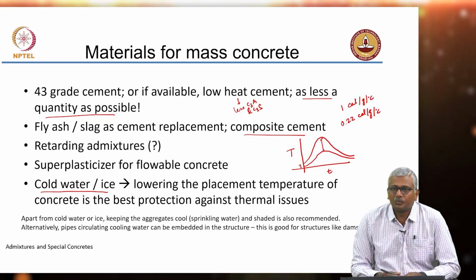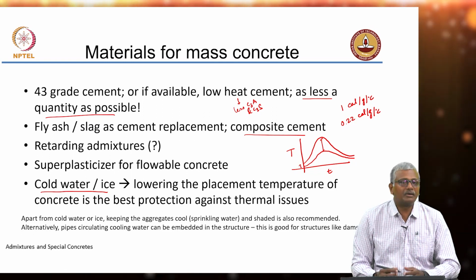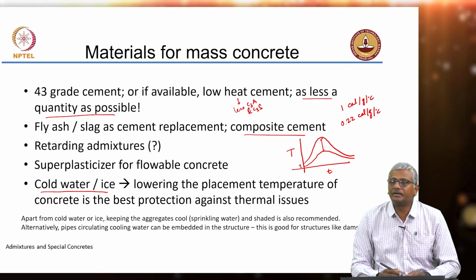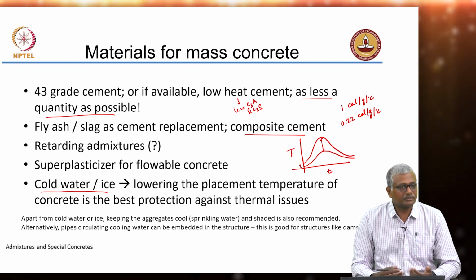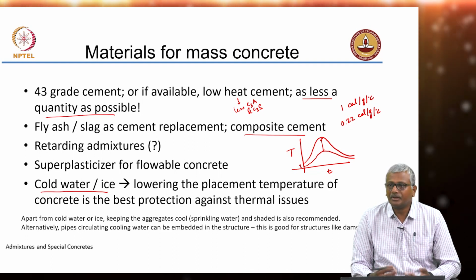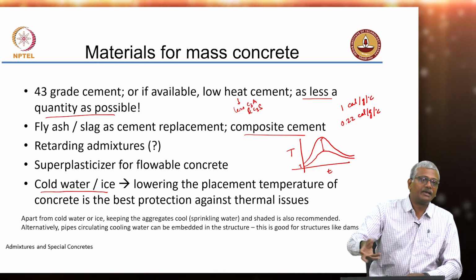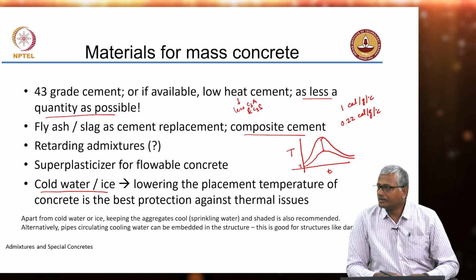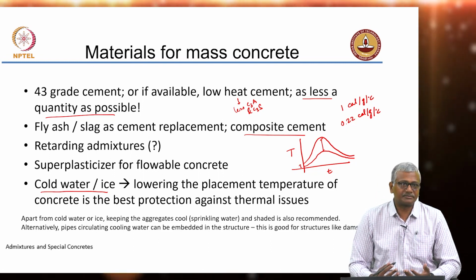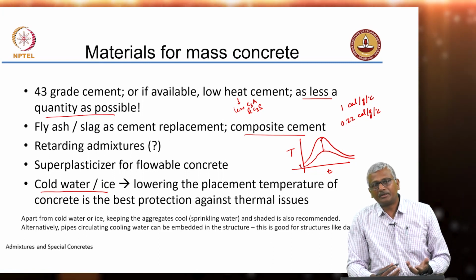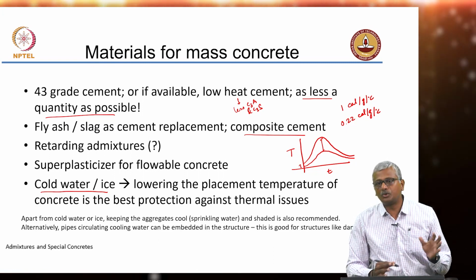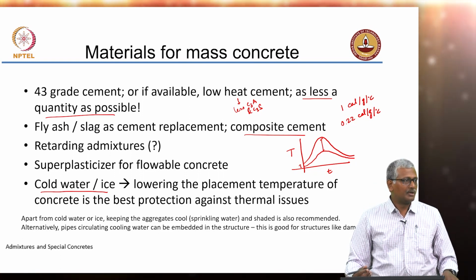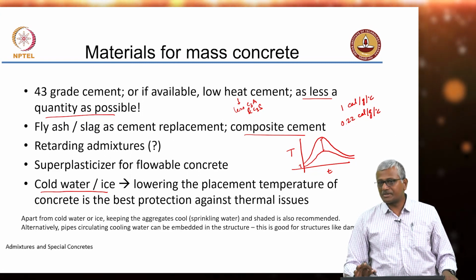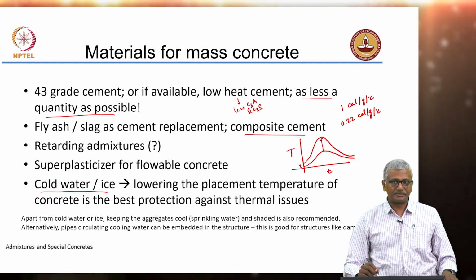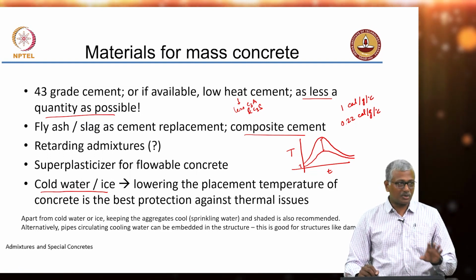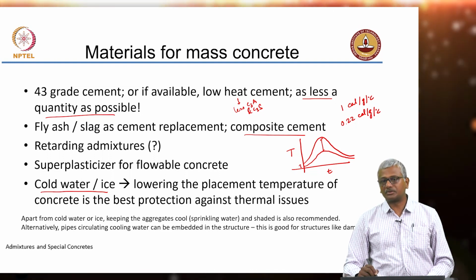Why is that? Why is cement hot? In large batching plants, the cement is transported from the cement plant. Do we get it in bags? No, we get it in bulkers, right? Fresh from production, the cement is taken in bulkers and stored in silos at the batching plant. The cement inside these silos can be quite hot, okay, because the bulkers can remove the cement. The bags obviously will be using cement which is cooled down to a certain temperature, but the bulkers can take really fresh cement. So the temperature of cement inside the silos can be sometimes as high as 60 to 70 degrees Celsius. Okay. So cement temperature will be very high. You need to keep that in mind while planning your concrete mixture.